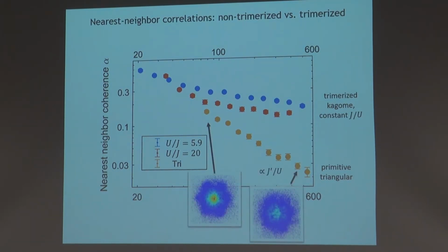So we take images like these, the diffraction images, the momentum space images, and we fit them with a function that would extract the nearest neighbor coherence along each of the directions. We average it up along the 3 directions that we observe. So that's what's meant by this nearest neighbor coherence function alpha. The simple case is, let's say, just the triangular lattice where all the bonds are the same. And if we drive the triangular lattice through the Mott insulating transition, then lo and behold, we see coherence washing away completely as we go into the deep Mott insulating limit.